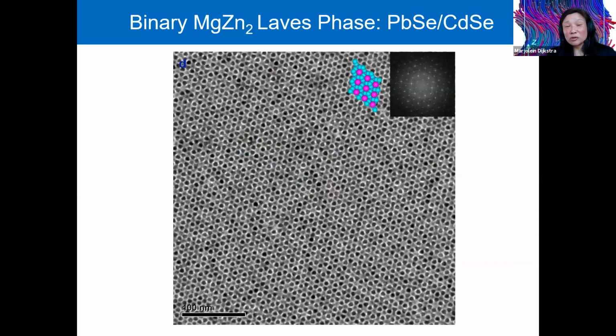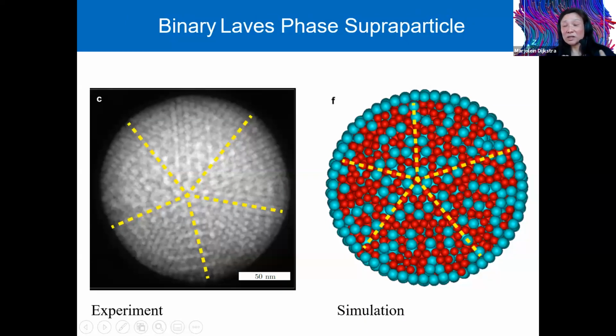Last but not least, we can also look at binary systems, binary mixtures of hard spheres in spherical confinement. We used the nanoparticles, the lead selenide and the cadmium selenide nanocrystals. They form in the bulk the most stable magnesium zinc Laves phase. If we put them in confinement, we find again this very beautiful five-fold symmetry, both in experiments and in simulations.